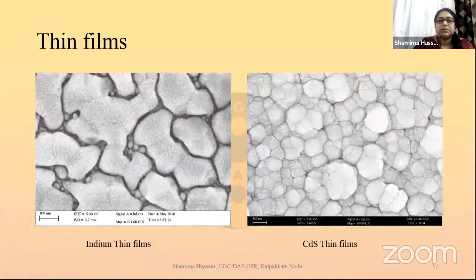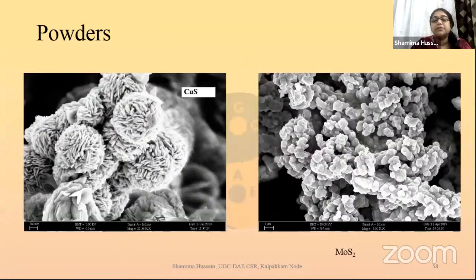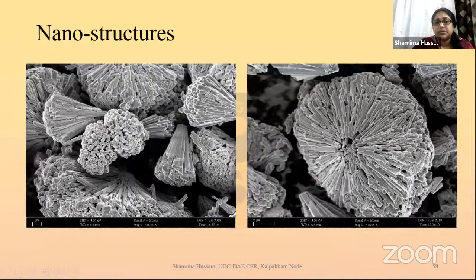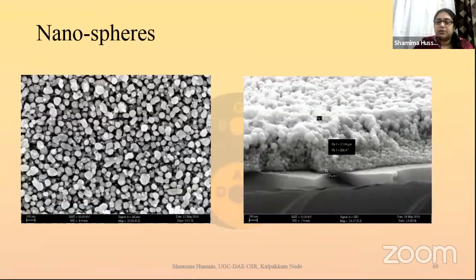These are some other examples. These are some powders. With powders, you get this kind of scattering because powders are loosely bound. If I could have them all bound together, I would not be having this kind of charging. These are some other nanostructures, some nanospheres. These are all grown. And in the SEM, you can also do some kind of cross-section study, so you can study what is the height. This is a substrate on which we have grown this film. And this is the height which we have calculated, something around 1.1 micrometer, which we usually do not want.